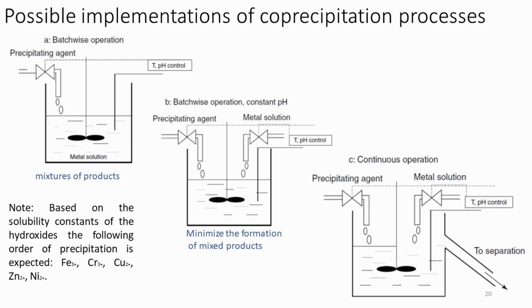Based on the solubility constant of the hydroxide, the following order of precipitation can be expected: iron, chromium, copper, zinc, nickel. This method can lead to a mixture of products not only different in chemical composition but also with different structure and texture properties.